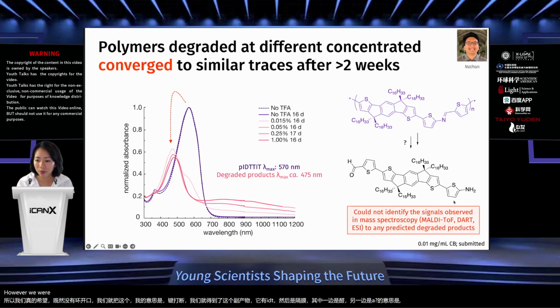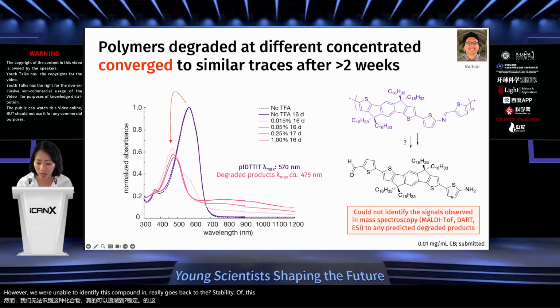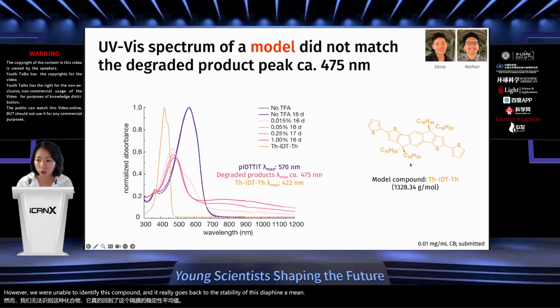However, we were unable to identify this compound, and it really goes back to the stability of this thiophene amine. So Shine went and made this compound here that's serving as our model to see where the shifts are. And it gives us a boundary limit. So this is your IDT TIT compound, IDT flank with thiophene, and this is our starting material, and our degradation product is somewhere in the middle. So we have something that is a little bit more electron withdrawing compared to this compound.